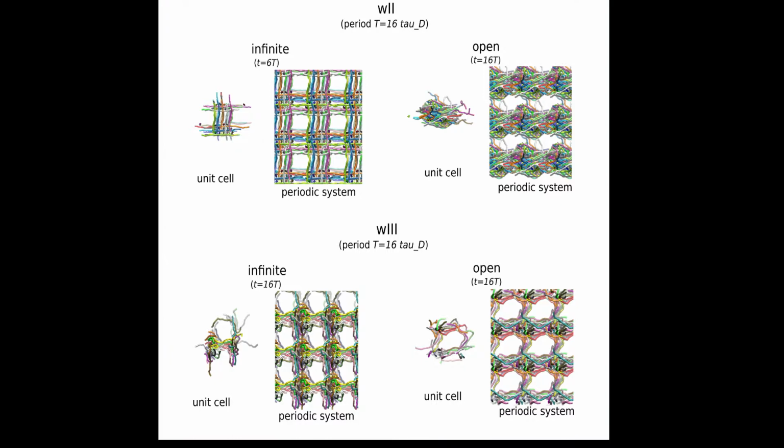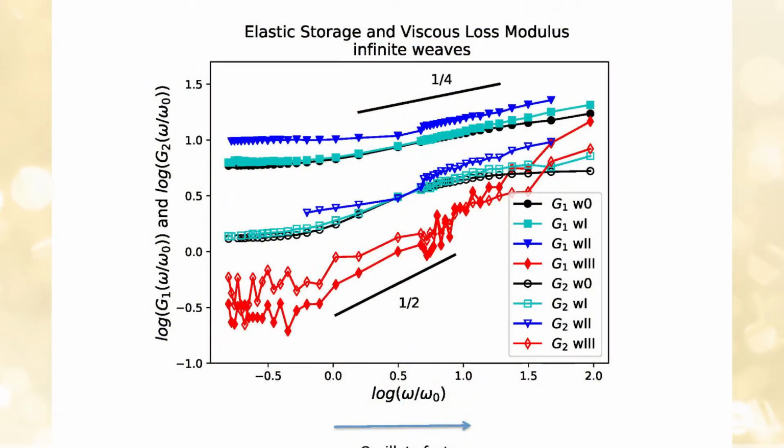And now what we do here is we oscillate faster, this way. You start oscillating faster. And you see in all these cases, the blue and black, the material is all the way, even for low frequencies, more solid-like than liquid-like. Okay? And this is something that is expected for cross-linked polymers. What are cross-linked polymers? Polymers that cannot change their conformations because their entanglements are actually links. So they cannot slide through each other. They are really bonded. And ours, since they are infinite, it is as if they are bonded to infinity, to something. Okay? So this is something that we could expect.